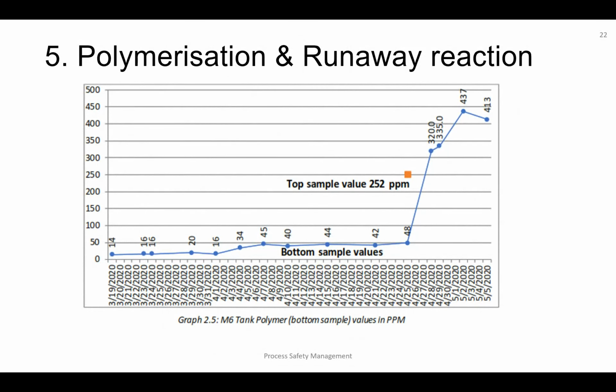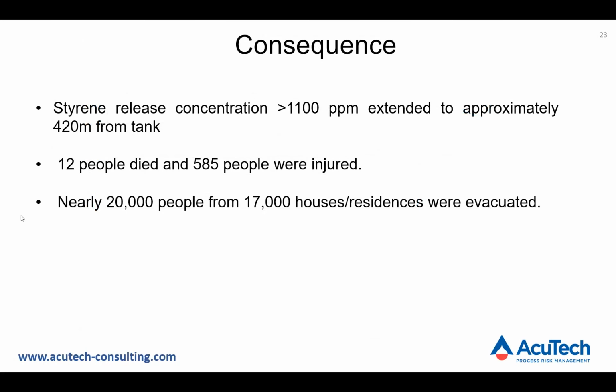Now this chart shows the increase in polymer formation over time, including the modest increase in the month prior to the incident, as well as the significant increase in the 2 weeks prior to the incident, which was a warning sign that should have triggered a response, but did not. Next, BJ will talk about consequences of the incident.